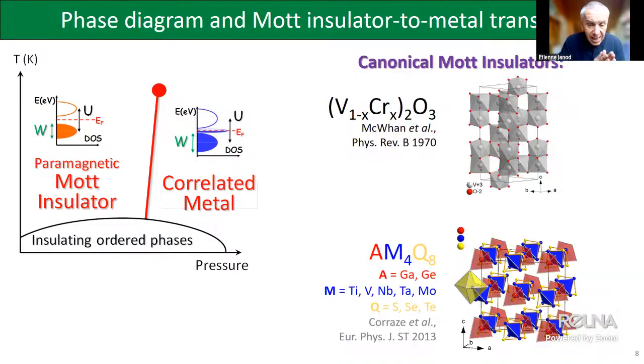What we can say is that, if we take the example of these two systems that we have here, especially vanadium, in terms of abundance, vanadium is somewhere in the middle. So it's one element which is not super rare, but on the other hand, it's not silicon or so. So in terms of abundance, vanadium is fine because what we have in mind is thin film, so the consumption is not super. We do not consume too much vanadium when we do this thin film deposition.